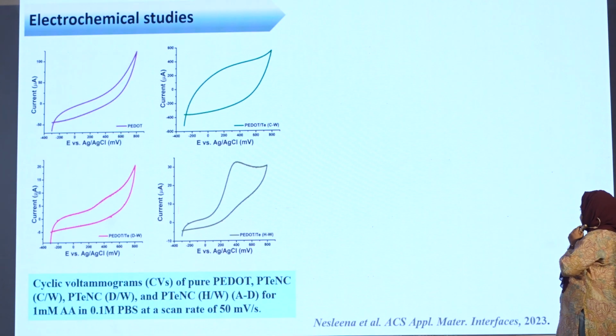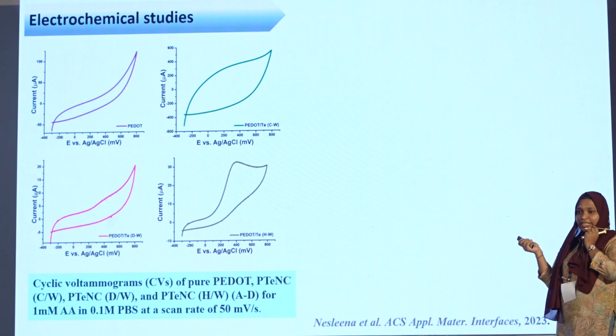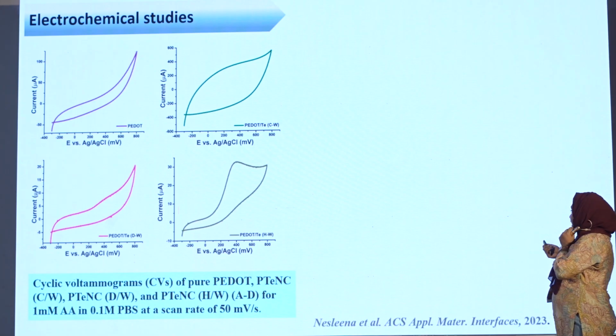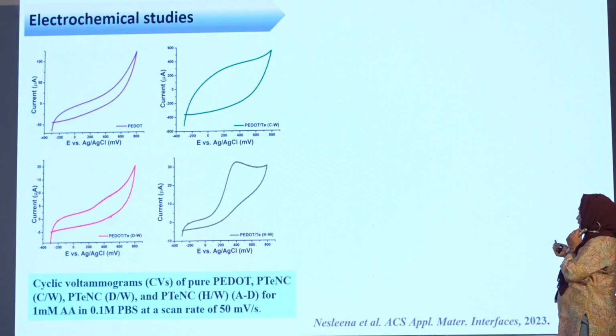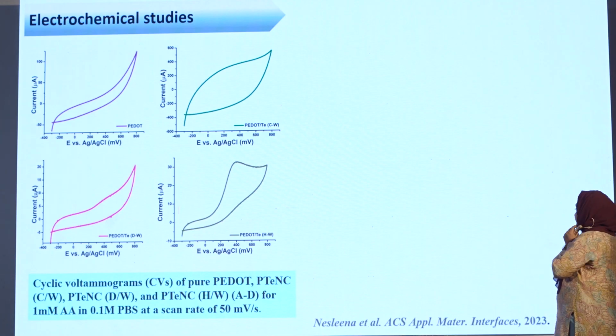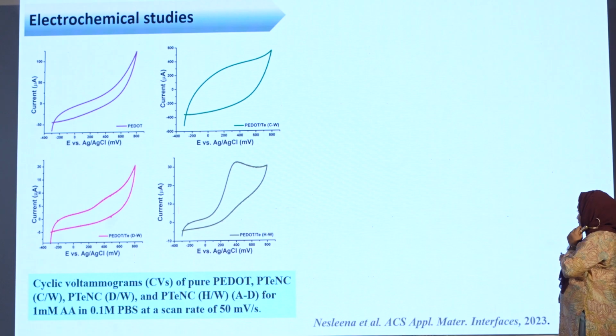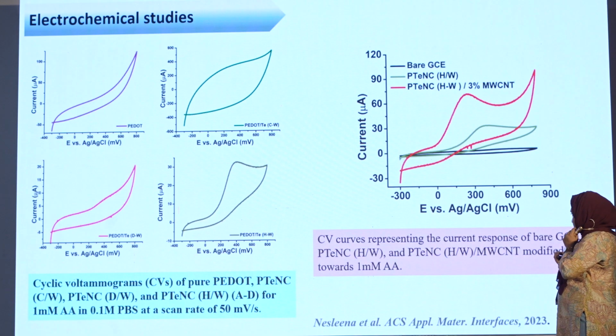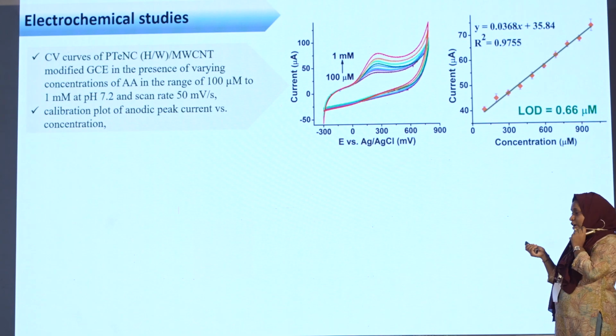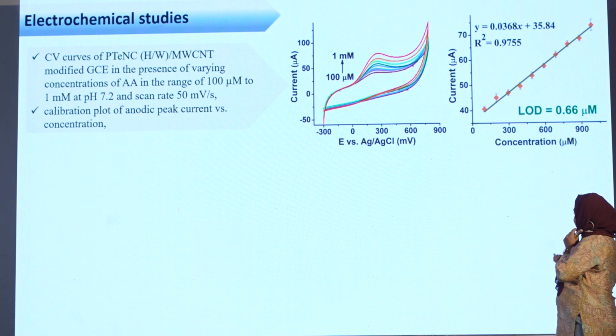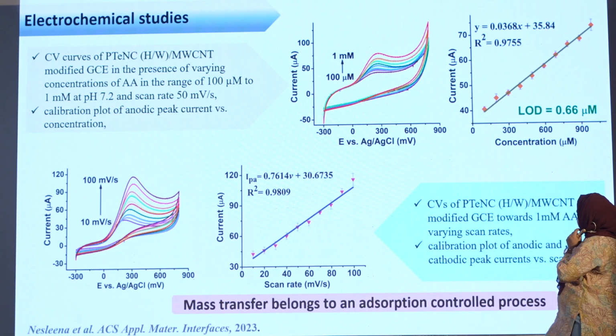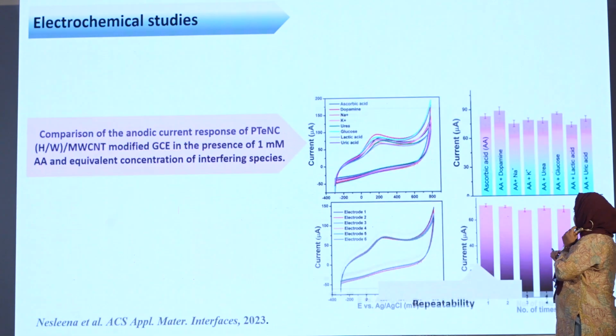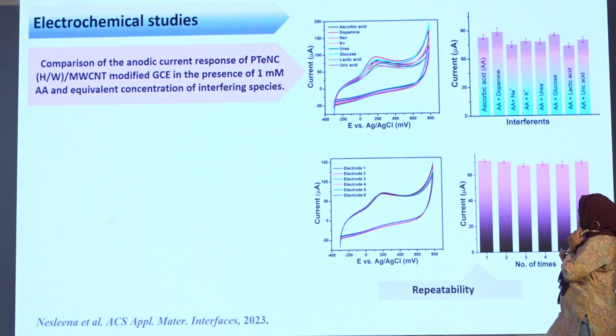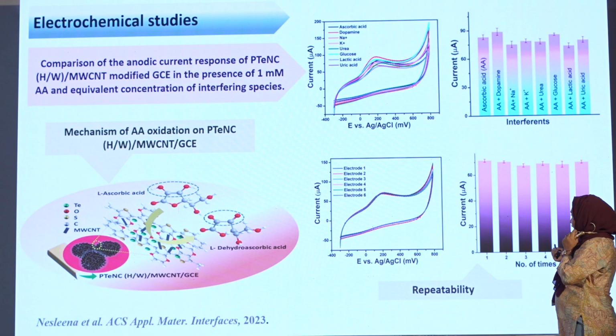We have also analyzed the electrocatalytic behavior, and PTeNC in CW exhibited a capacitive behavior, whereas PTeNC HW showed an oxidation peak for the electrochemical detection of ascorbic acid. Then linear range studies showed an LOD of 0.66 micromolar. With the scan rate analysis, it showed that mass transfer belongs to an adsorption control process. Anti-interference studies and repeatability studies were also done, and the mechanism of AA oxidation on PTeNC is also given.